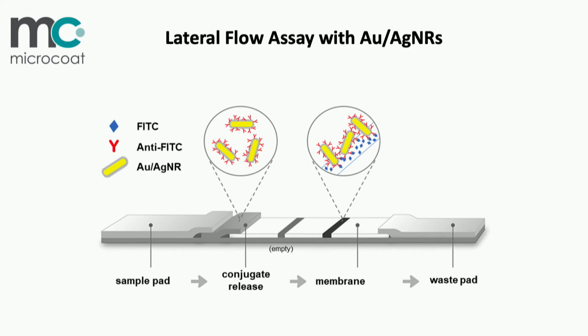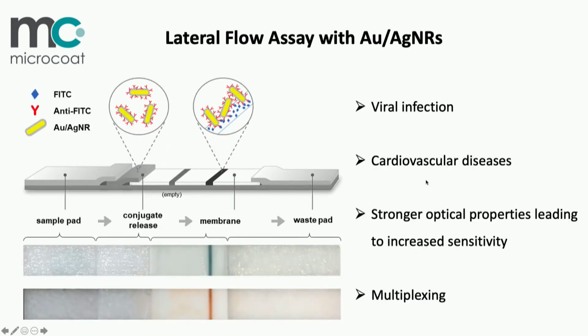What Lynn and Max then did with their partners Microcoat is to test the nanorods in a lateral flow assay, so have the nanorods coated with an anti-FITC, and as they encountered the FITC on the membrane, the rods would accumulate and you could see a color. As you can see here, we did it with 2 different colors of nanorods, and the plan is to detect viruses but also cardiovascular diseases, because these strips are just so easy to use, so economical, and you get an answer within minutes. The stronger optical properties of these nanorods, we are hoping, lead to increased sensitivity and give us the ability to do multiplexing, so different colors at the same time, different viruses at the same time on the same strip, for example.